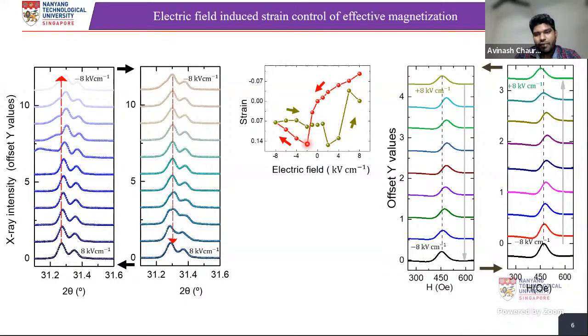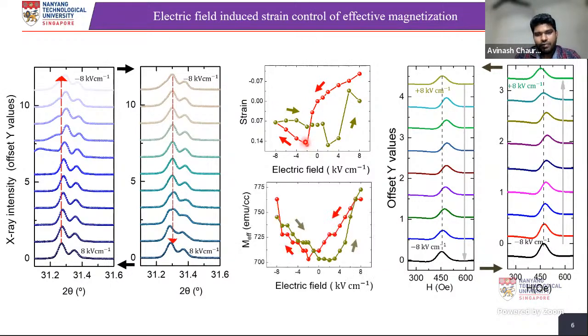So we did the FMR spectrum measurement at different electric field, and then we find that this also forms a butterfly behavior. So this clearly indicates that we can directly correlate that the strain can control the effective magnetization of the ferromagnetic layer. So now, after confirming this, that strain can control the effective magnetization, we use this system to do the terahertz spin current measurement by applying different voltages.